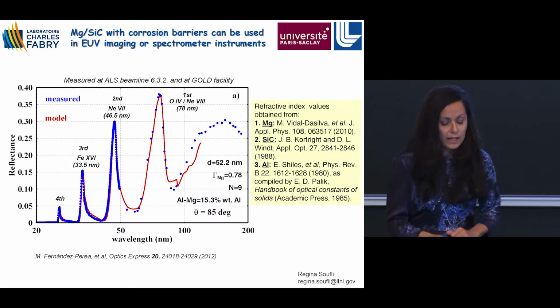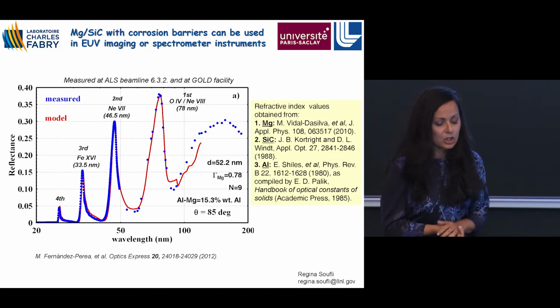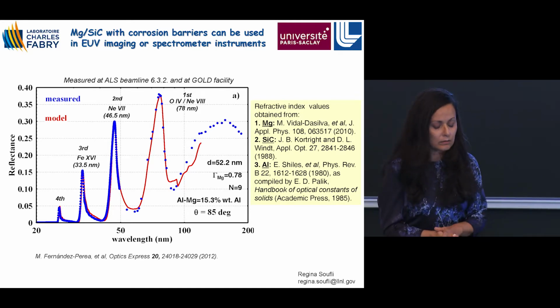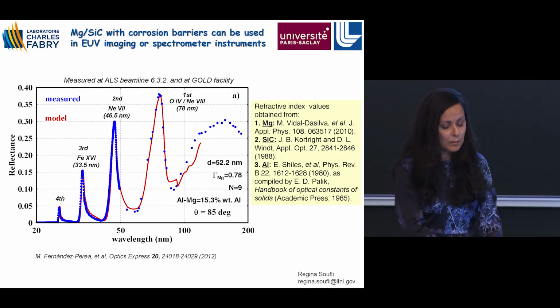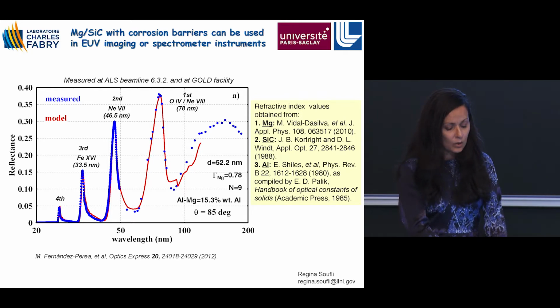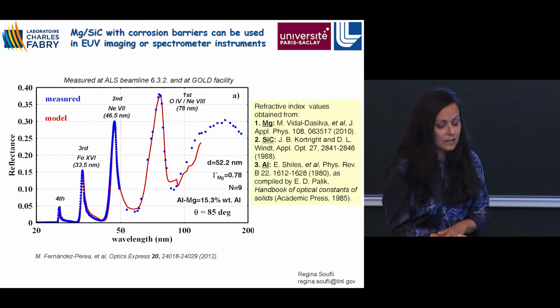So as I mentioned, we implemented this coating in actual multi-layer coating designs. This is just an embodiment, just to have fun. We planned the first Bragg peak of the multi-layer to be at an oxygen neon plasma line, and the second Bragg peak at another neon line at 46 nanometers, the third Bragg peak at an iron plasma line. Of course, again, this is an example.